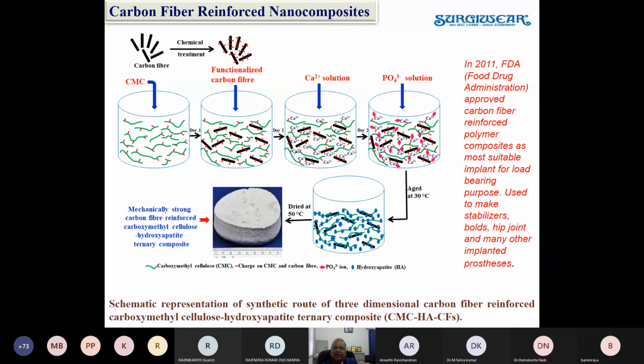bioactivity, but we were not getting close to the bone modulus, that is, of the cortical bone, the hard part of the bone. So what we did was use orthopedic grade carbon fiber and reinforce our polymer matrix with it before going for the hydroxyapatite precipitation in it. So we could develop a product which has the mechanical strength, especially the modulus, of the order of the bone. And this process was also immediately taken by Surgiwear.